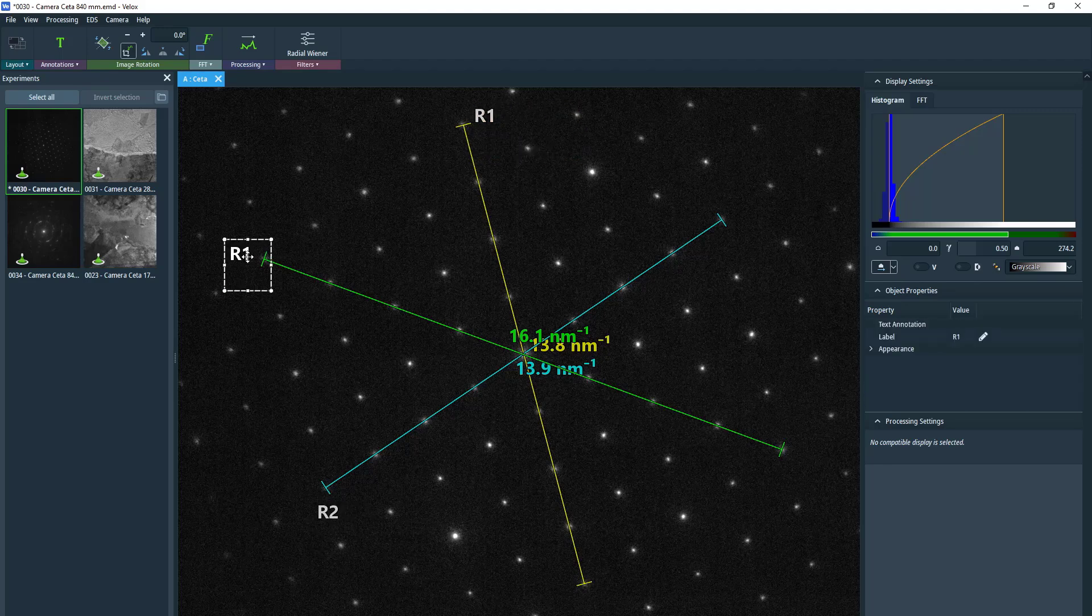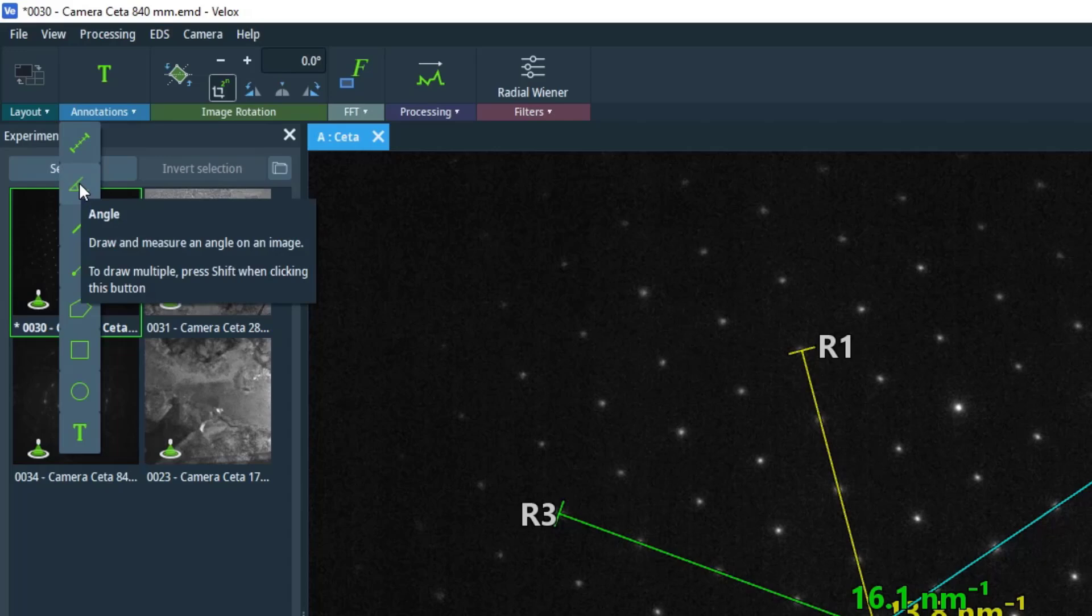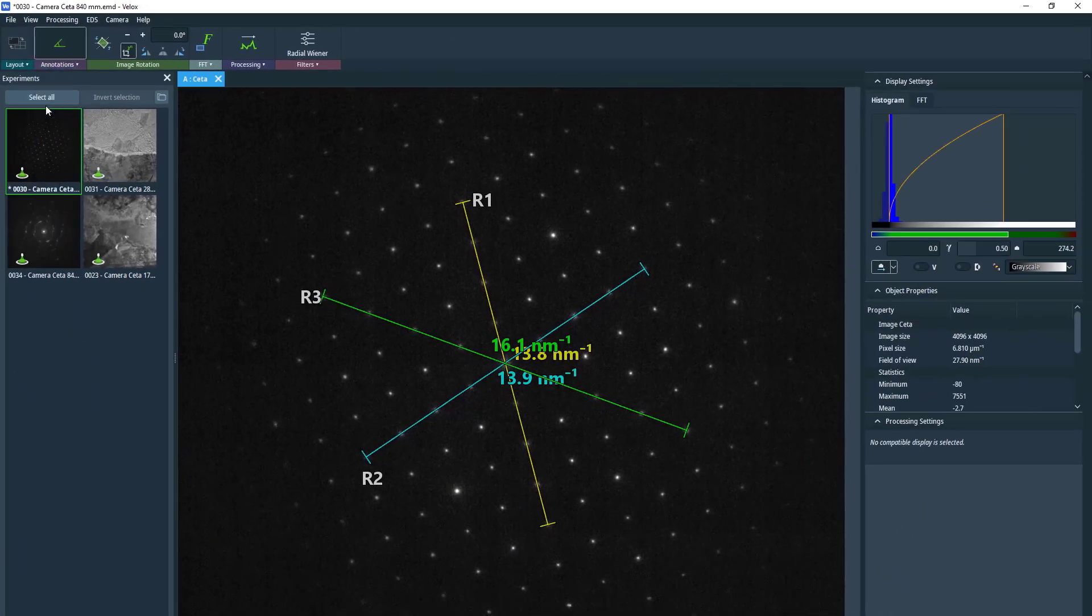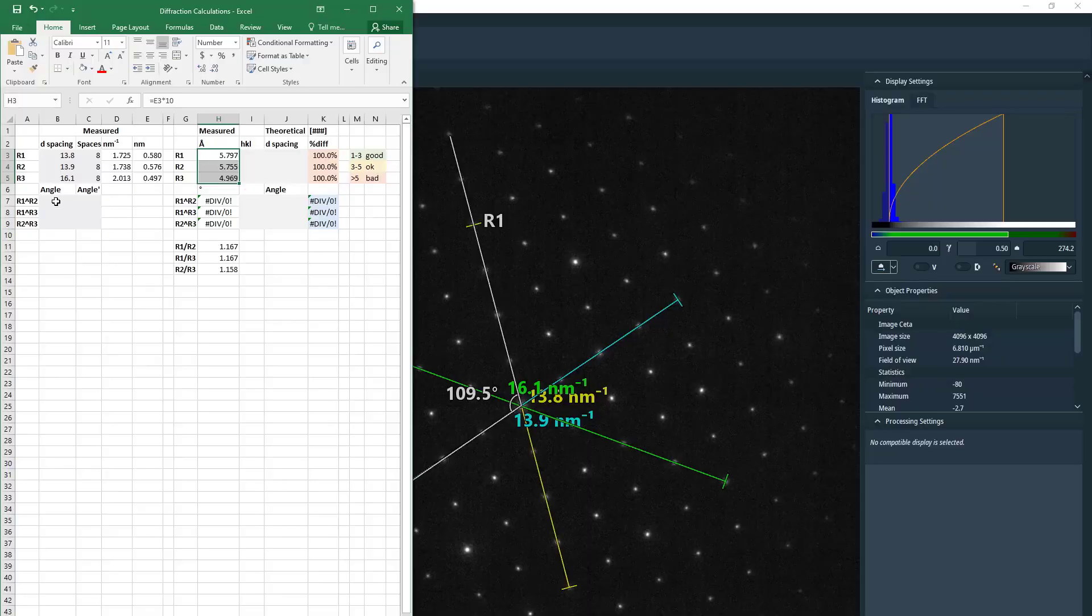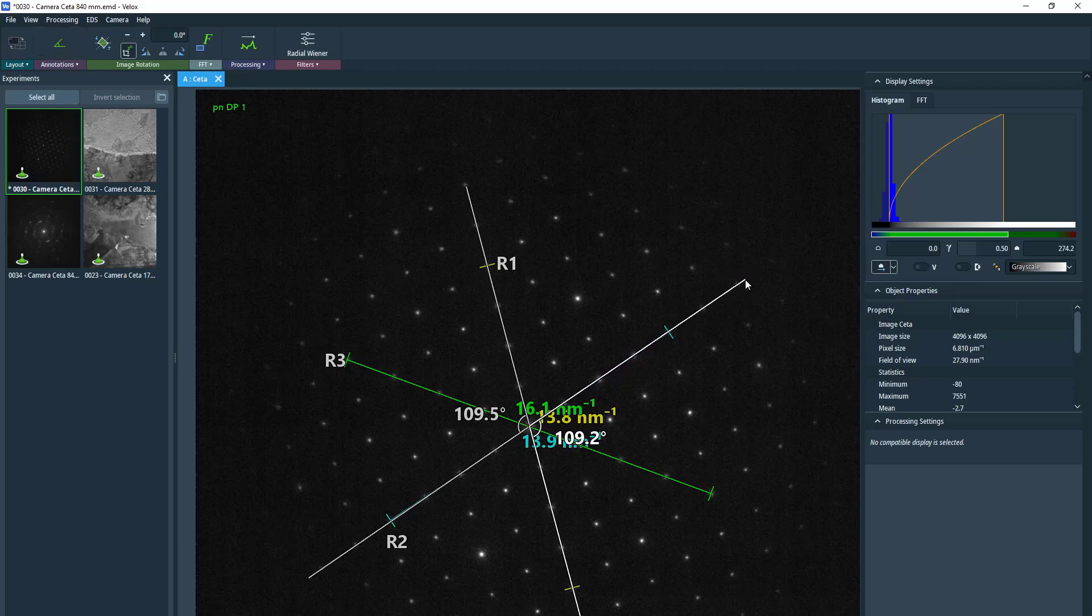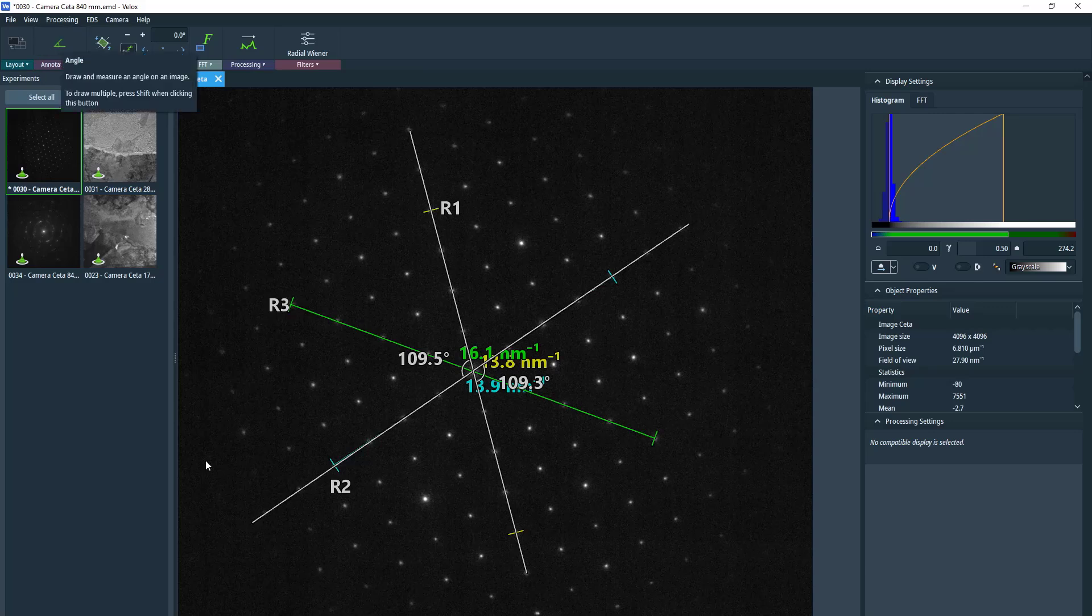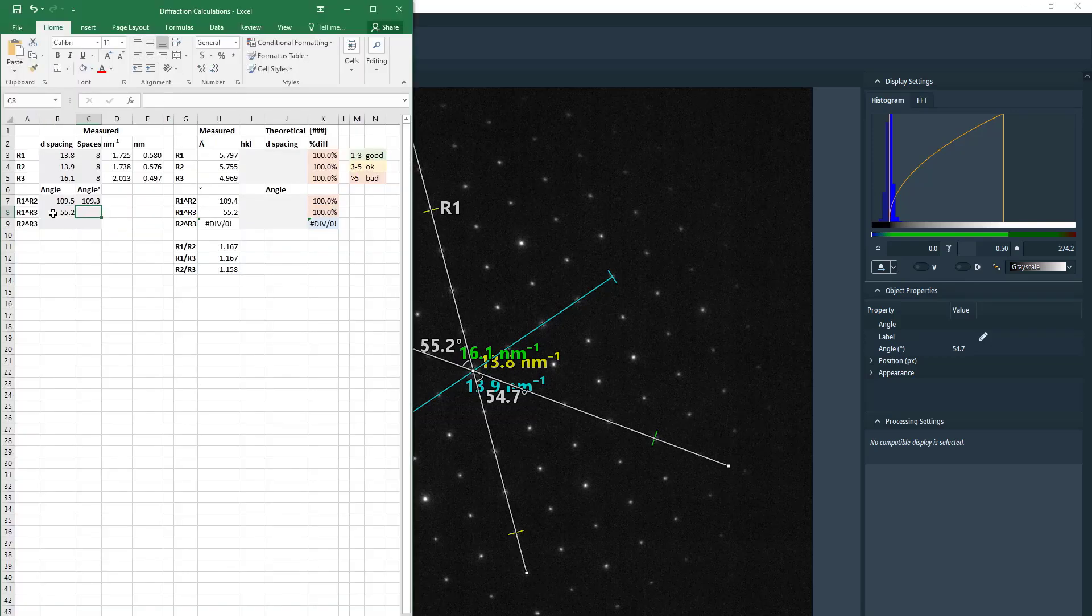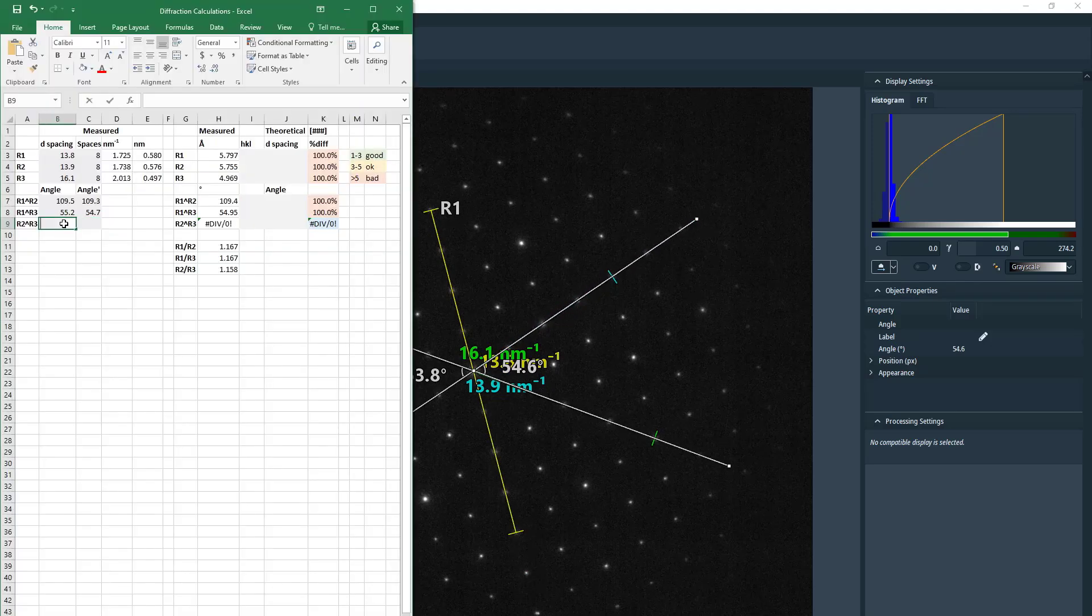Because remember, R1 is the one that looks the smallest in reciprocal space, but is the largest in real space. Once we've assigned these, we can now measure the angles. I'm using the angle tool within Velox, and all I do is follow the R1 line, the R2 line, and I put the center spot on the transmitted spot. I then type in my angles, and this is actually more accurate if you do it on both sides of the central transmitted spot. I have the two basically symmetric angles, and I'm now doing it for R1 and R3 on both sides, and then R2 and R3. This spreadsheet takes the average of those two.